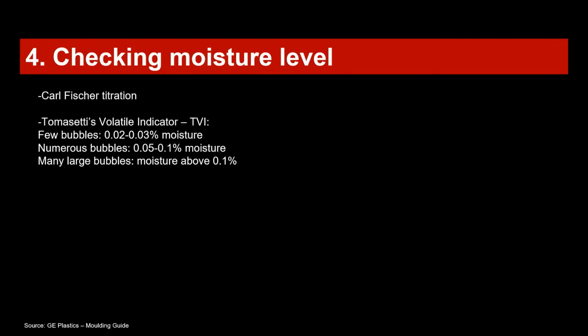You can have few bubbles, so this means you have a moisture content of 0.02 to 0.03%. Then numerous bubbles, so there it's already between 0.05 to 0.1% moisture content. And when you have many large bubbles, then the moisture is most probably above 0.1%, and another drying needs to be done. And for that you usually need a hot plate, where you place the pellets to heat up, usually on a glass plate. The glass plate onto the hot plate and the pellets onto the glass plate.